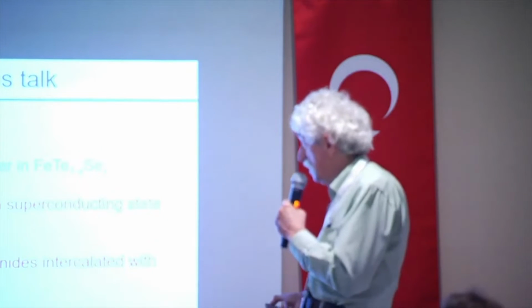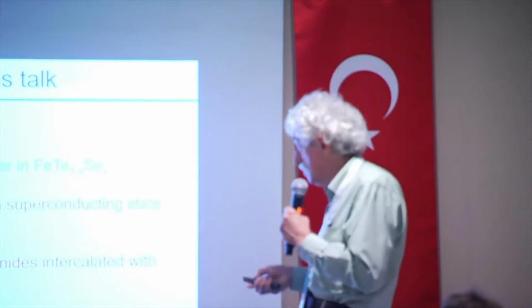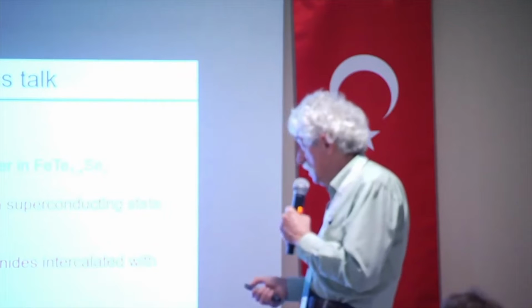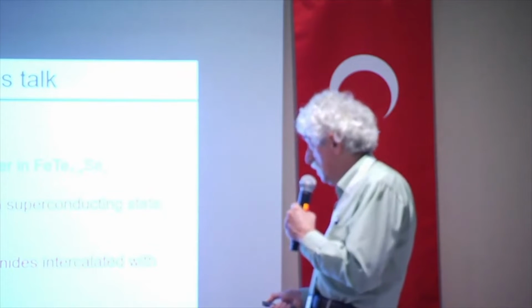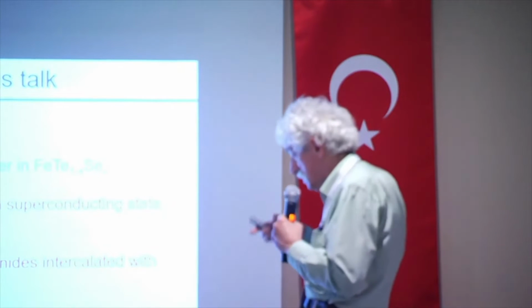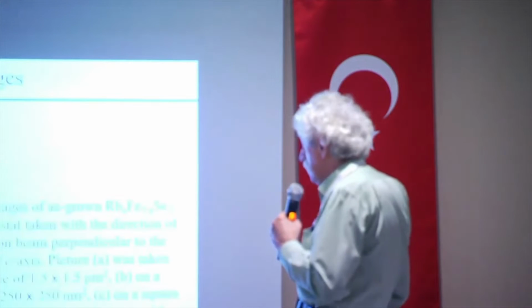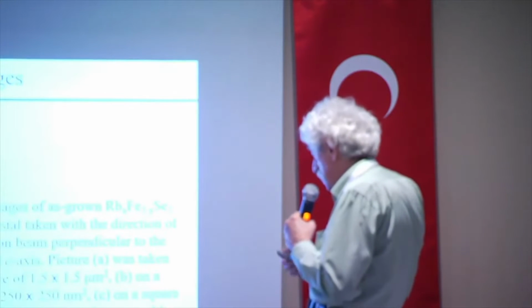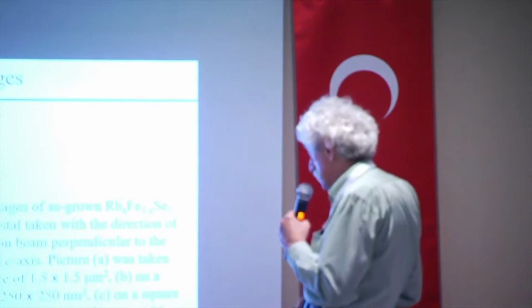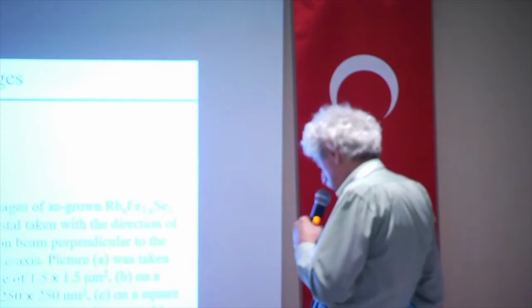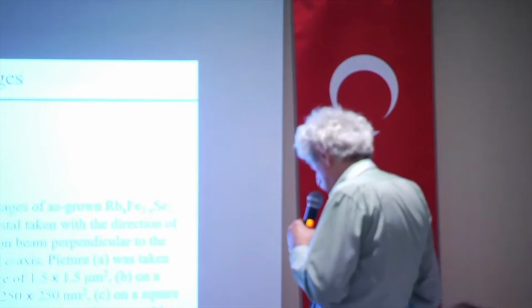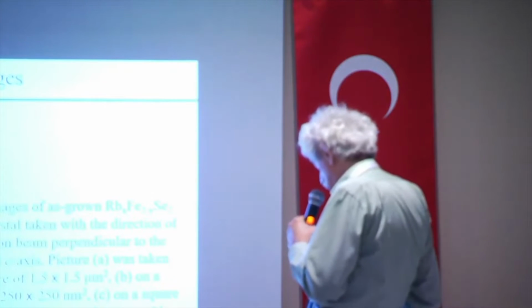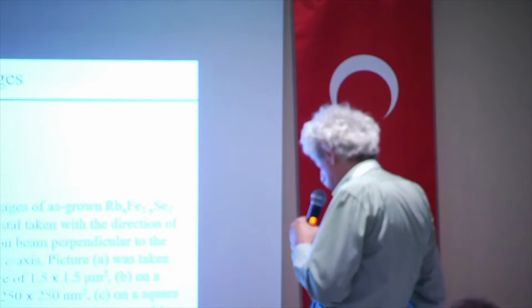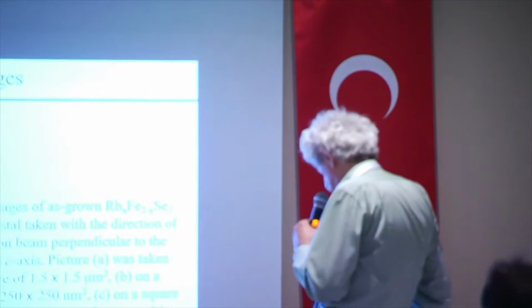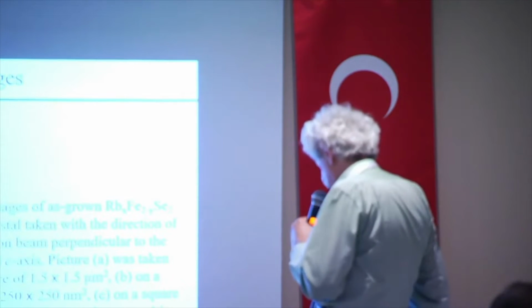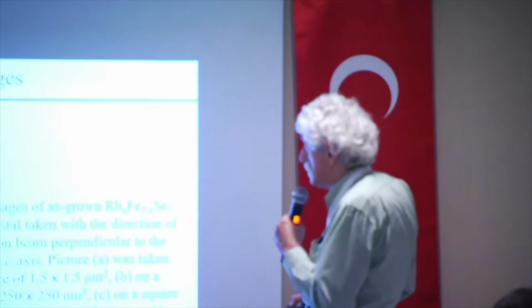This material is rubidium intercalated iron selenium. The crystal formula is rubidium iron 2 minus x selenium 2. For such materials, there is a scanning transmission electron microscopy image. You have basically two phases. One phase is, for example, rubidium 0.5 iron 2 selenium 2, but it can be rubidium 0.5 iron 1.6 selenium 2.